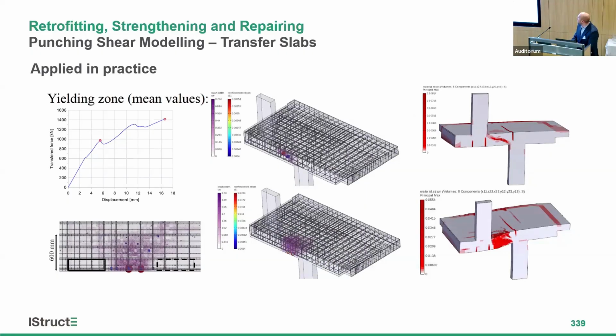The nonlinear analysis can be used to model transfer slabs and better understand their behavior and capacity. Normally, nonlinear analysis shows additional capacity compared to simplified conventional methods. However, this example shows that between the misaligned columns at the edge of the slab, most of the stress is very, very concentrated in a really narrow band of slab. On the left-hand side, you can see that two shear links are engaged.